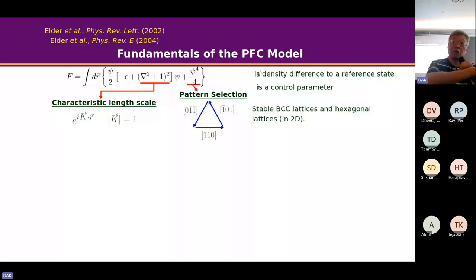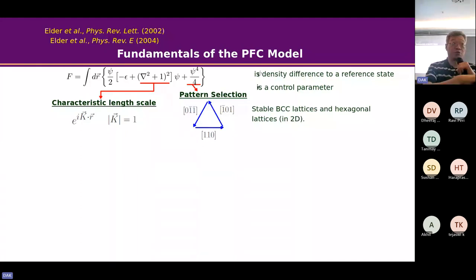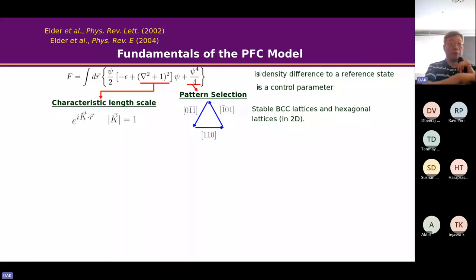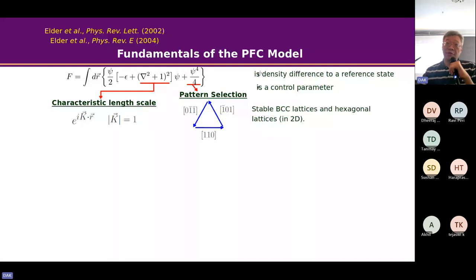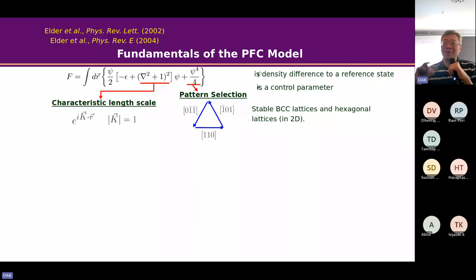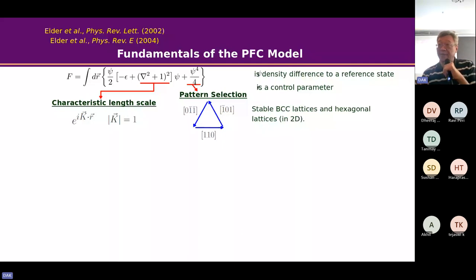When it becomes a liquid, it's basically a constant — there's no structure. So it's a little bit different from phase field modeling, because in phase field you have two equilibrium values representing the solid state and liquid state — maybe psi equal to 1 is solid and 0 is liquid, but in the solid it's just a constant. In phase field crystal modeling, you can see oscillations, and each oscillation represents an atom.